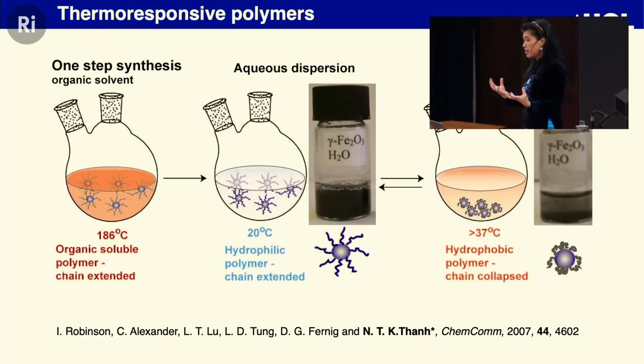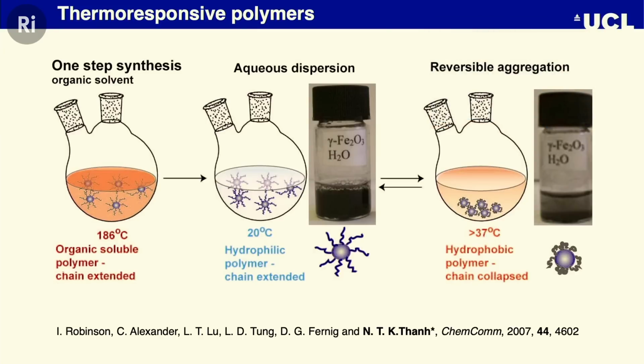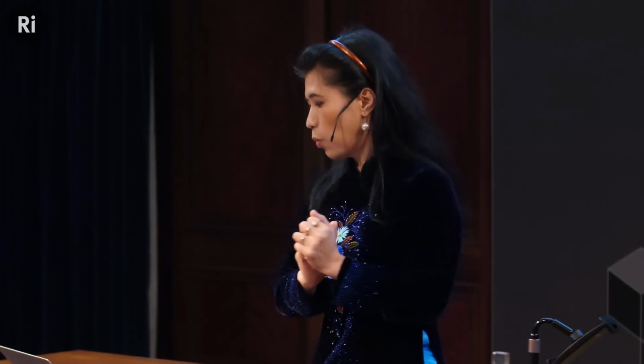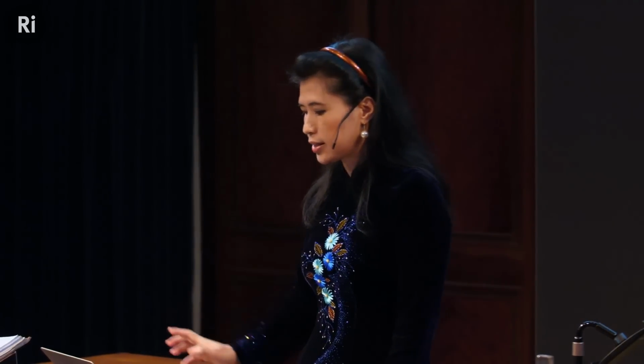And it was a great excitement, which I did not know before, that we could make the nanoparticle with a thermoresponsive polymer. It turned out really interesting because this thermoresponsive polymer dissolves in a hot organic solvent. It allows you to do the reaction because at the higher temperature the nanoparticle is more crystalline, the crystal structure is more ordered, and it becomes more magnetic. And you can let it cool down, and it changes phase because it responds to the temperature, and this changes the conformation of the polymer. Then you can remove all the hot organic solvent and disperse them into the water, right? So what next?